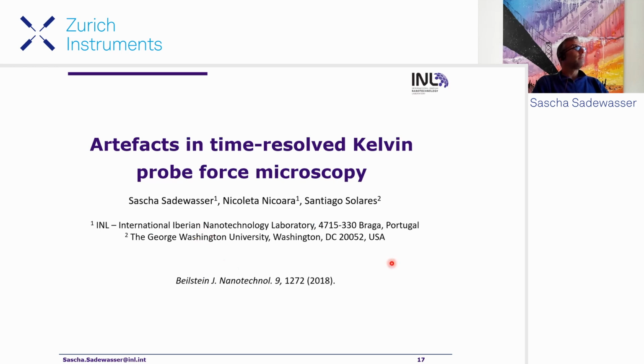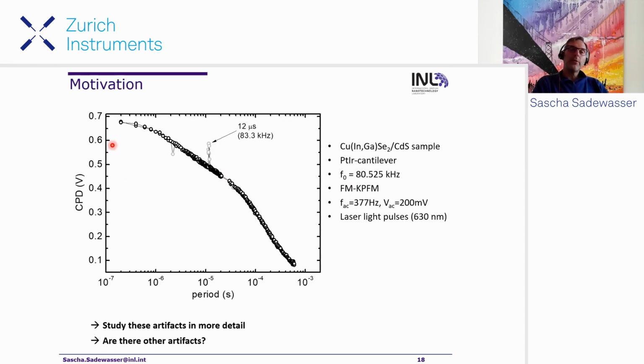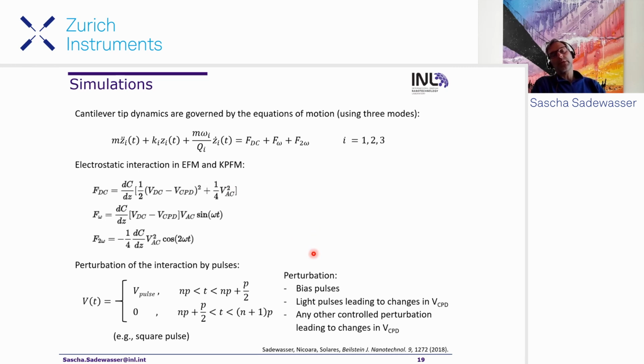So finally, I want to put a few slides here on the artifacts in time resolved Kelvin probe force microscopy. I see my time is not too much anymore, so I will go slightly quicker. When we do these spectra, sometimes we see these sparks here and normally we try to ignore them, but then at some point we just got interested and tried to understand these kinds of things a little bit more. Here it's probably related to the resonance frequency of the cantilever. So we teamed up with Santiago Solares, who has previously looked at the cantilever dynamics by just looking at the equation of motion of the cantilever.